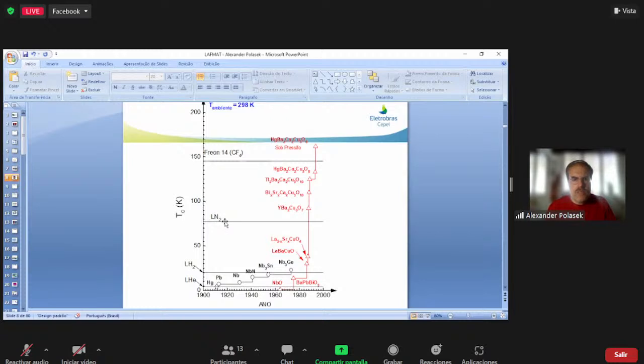And it was amazing because there is a big difference between using liquid helium or liquid nitrogen, because liquid helium is much more expensive and not so abundant as liquid nitrogen. In the middle, you also have liquid hydrogen. But, as I will show you, not all applications can use liquid nitrogen because it depends on the magnetic field, because the critical current is a function of magnetic field. If the magnetic field is higher, you need to reduce the operational temperature.